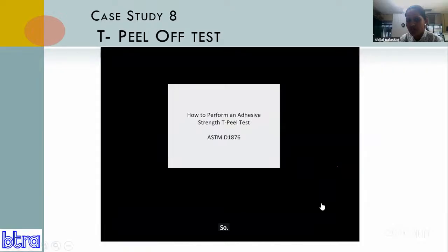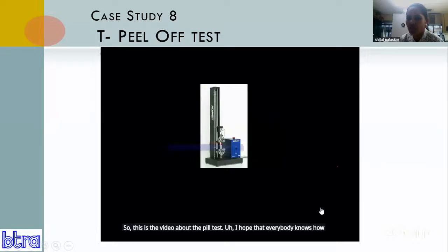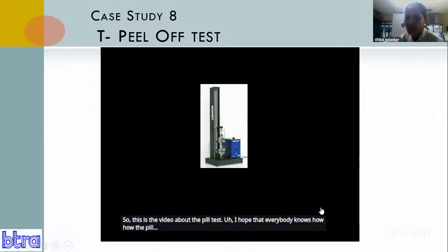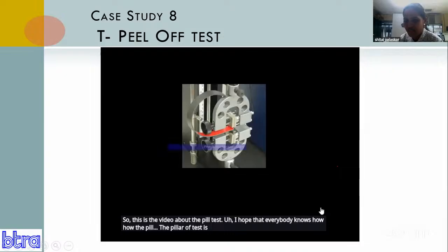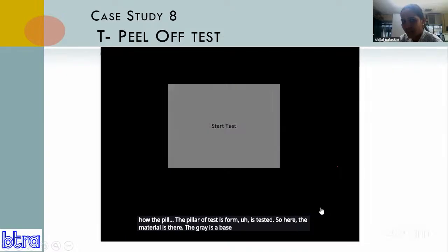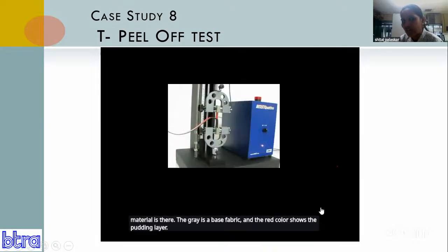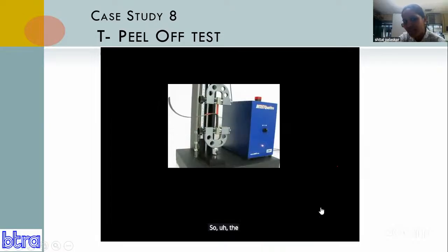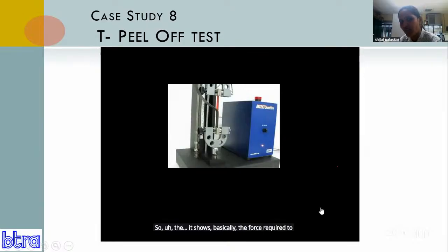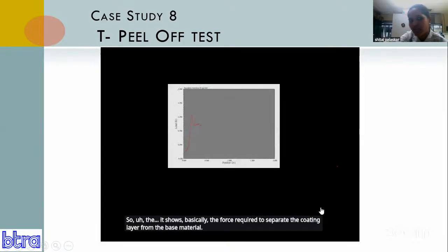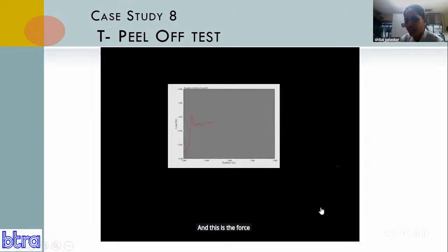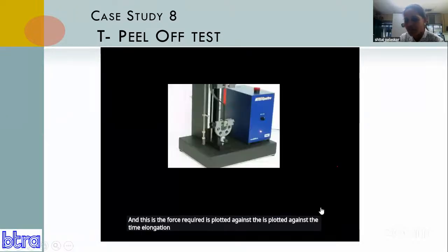So this is the video about the peel test. I hope that everybody knows how the peel-off test is tested. So here the material is there. The gray is the base fabric, and the red color shows the coating layer. It shows basically the force required to separate the coating layer from the base material, and this force required is plotted against the time elongation. So this is the adhesion test.